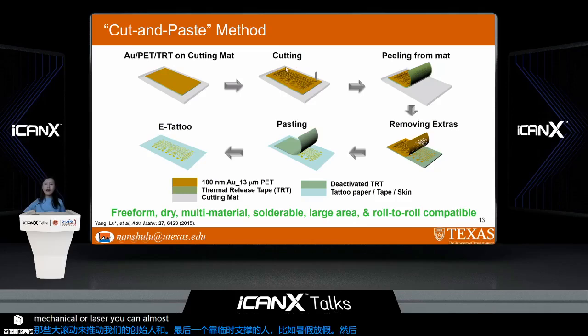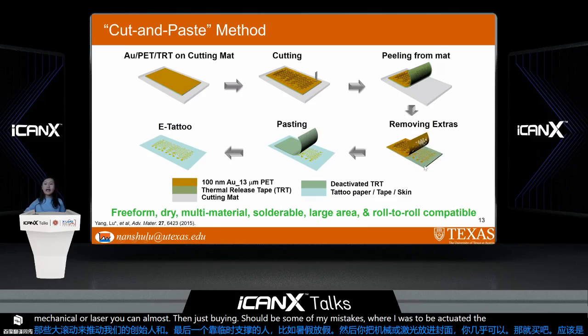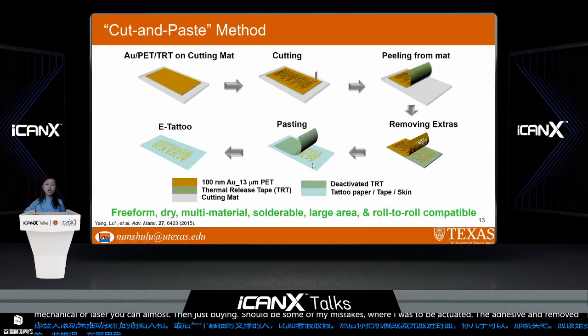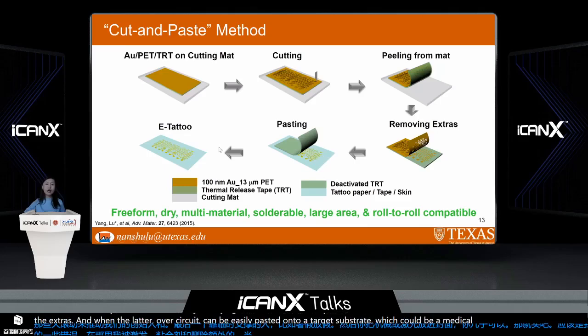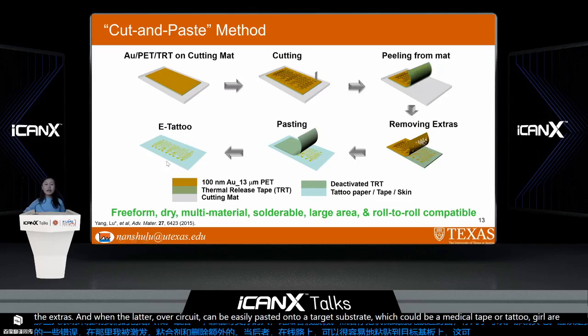And then just by heating the thermal release tape, we're able to deactivate the adhesive and remove the extras. And then the leftover circuit can be easily pasted onto a target substrate, which could be a medical tape or a tattoo paper or directly on our skin. The whole process only took us 10 minutes, and it is a completely freeform and dry process, as you can see.